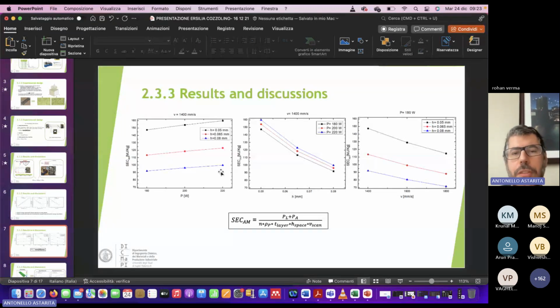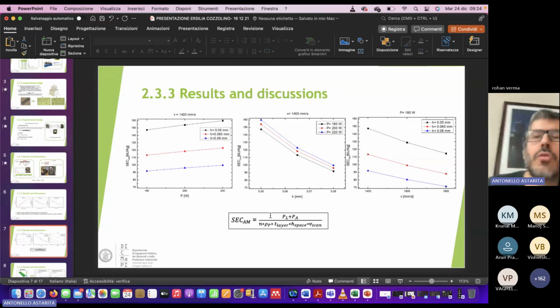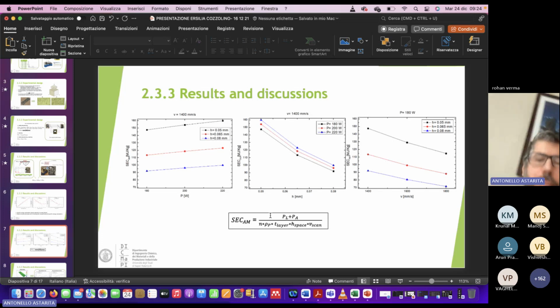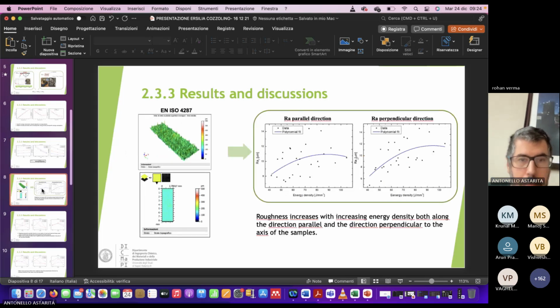Okay. Each of these diagrams is produced by fixing one factor and varying the others. So you can see that the formula that is portrayed here is good in catching the experimental development of the process. So you can use this formula to adjust the choice of the process parameters, to choose the processing conditions that are the best relating to the specific energy consumption of additive manufacturing processes.